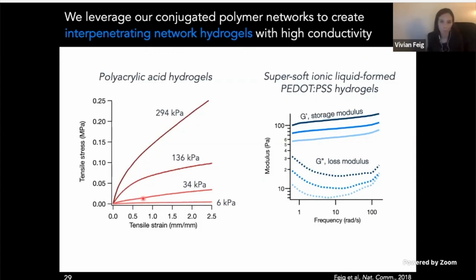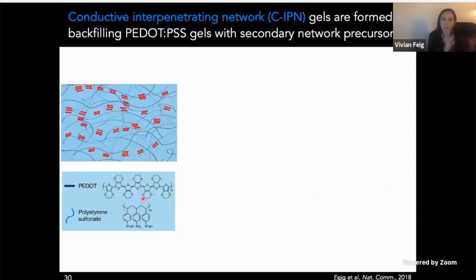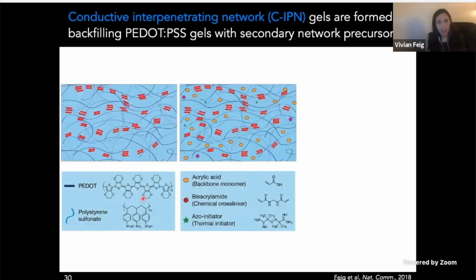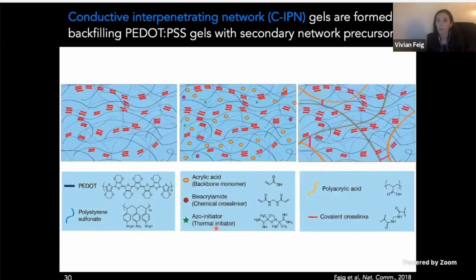And so to actually interpenetrate these two networks, we start by molding the soft and conductive PEDOT:PSS gel, and then backfill the gels with acrylic acid monomers, bisacrylamide as a chemical crosslinker, and then this thermal initiator that activates at 60 degrees C. And so after heating, we then have this polymerized polyacrylic acid, and the resulting material we call CIPN, or conductive interpenetrating network gels.